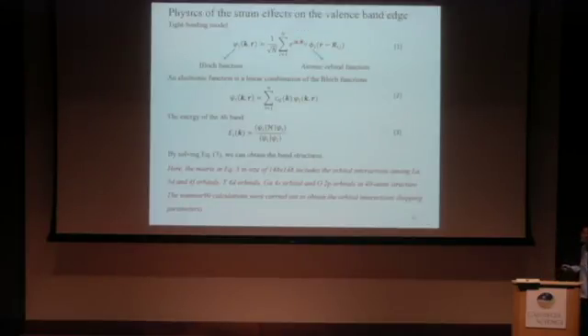And to study how the band gap character changes between the two phases, we rely on the tight-binding model, in which the Bloch function can be expressed in terms of the atomic orbital function, and then an electronic function can be a linear combination of the Bloch functions. Then we can finally obtain the energy for each band at a k point, expressed as this secular equation.